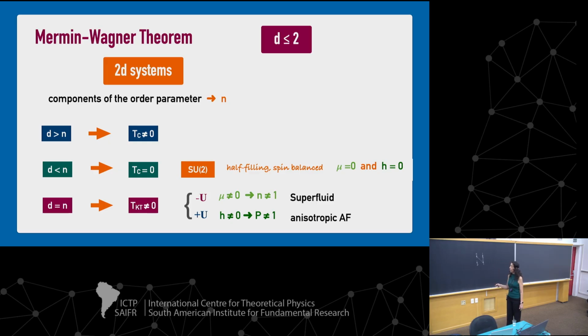If you have the dimension smaller than the number of components of the order parameter, which is what happens in isotropic antiferromagnetism, where your spin can point in any direction, and you have X, Y, and Z components, so you have 3 components, which is larger than 2, the dimensionality, then TC equals 0.